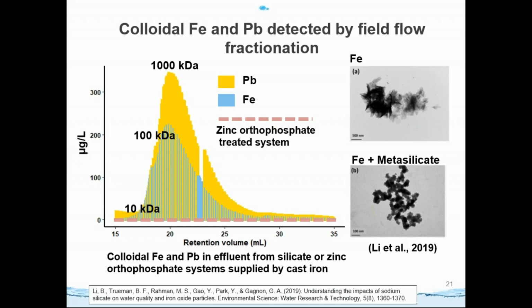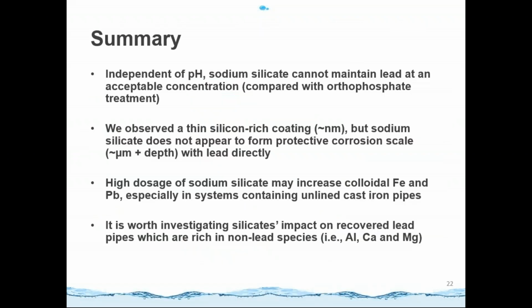In our previous study, I cited two figures from the literature. We find that the presence of sodium silicate can increase the dispersion of iron. So we suppose that when we overdose the sodium silicate, the increased dispersion of iron can result in high lead and iron concentration in the effluent of the municipal pipe system. Colloidal iron has a stronger correlation with elevated lead release in the full or partial lead service line pipe. So let's go to the summary.